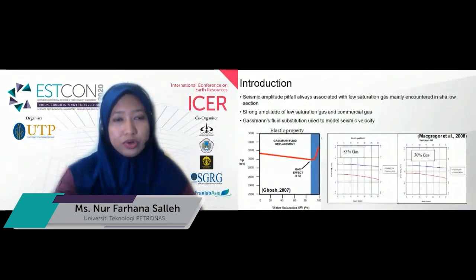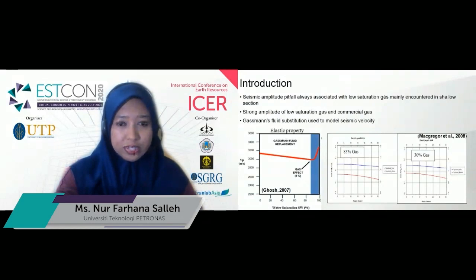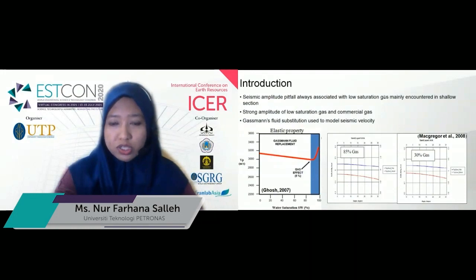The change of rock elastic property to gas saturation can be demonstrated using the Gassmann fluid substitution equation. We can see from the lower left figure by Ghosh in 2007, from 0 to 5% of gas inclusion, the compressional velocity drops strongly, giving rise to strong amplitude in seismic. Another study conducted by McGregor in 2008 assessed the reflectivity change between 55 and 30% of gas. From the results, we can see the seismic amplitude can only differentiate between the wet case, in the blue curve, and the gas case, in the red curve. But between 55% and 30% of gas, the reflectivity change is almost similar, showing increasing negative reflectivity from 0 to minus 0.1 for both cases.